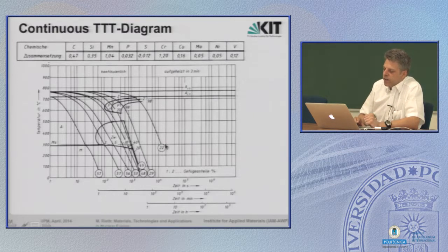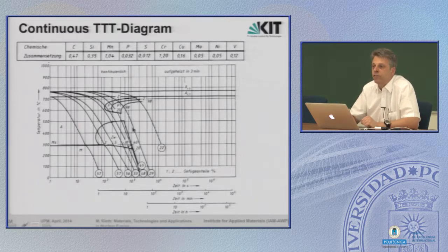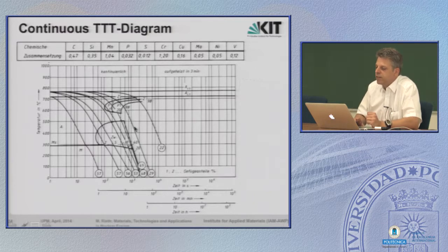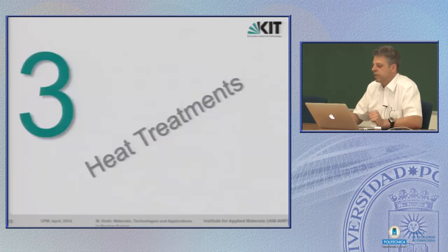And interesting is a further technical information. All these lines end with a number. And this number gives you the hardness where you end up. Low numbers are soft, high numbers are hard, strong materials. You see, pearlite, ferrite, that's a very soft material. And here, 57, that's a hard material. So already here you see, martensite is a very hard phase, whereas pearlite or ferrite is a soft phase. But still, it's one and the same steel. We haven't changed anything in the chemical composition, just by different cooling rates starting from the austenitic phase.